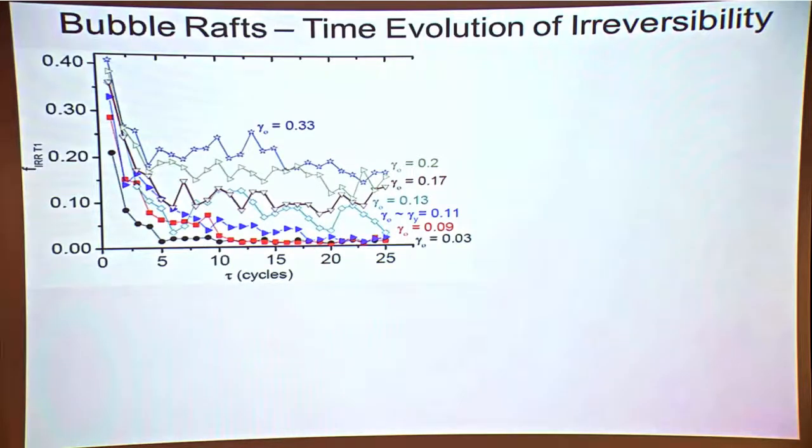Yes, George. Related to that, in other experiments, for example the experiments that you saw with the DWS, essentially you measure the reversibility by light scattering, and that is quite sensitive, not only to whether the neighbors are the same, but whether the distances are the same. So when we say 100% reversible, it means the whole structure has been exactly the same. Then it's fine. Absolutely. And we do relate this also to the previous experiments by Pine and Pascal. There was also another group that did the same experiment in DWS, I think Cohen had done something like that.